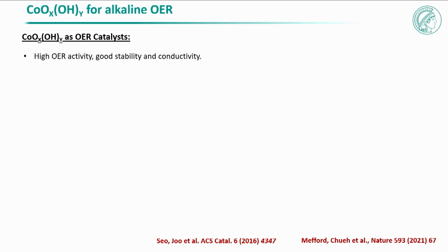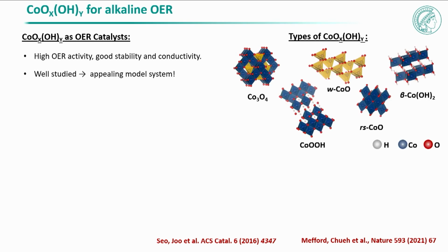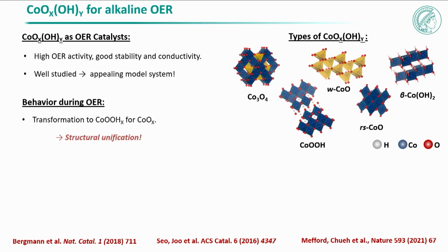So what can we do in research, right? We already know there is an electrolyzer and there are some materials that work. What are still the things that we can do? So there have been a lot of studies, even for these very nice cobalt oxide or cobalt hydroxide catalysts. There have been a lot of studies trying to make different pre-catalysts with different structures, with different compositions. And unfortunately, what we realized is that there was not much difference in what was coming out, because under reaction, there is a structural unification.